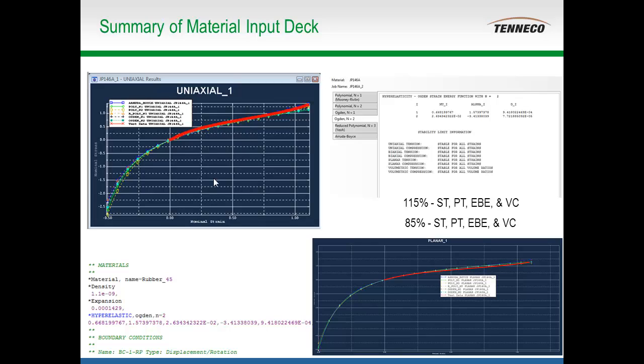So on to the Abaqus analysis. So we take that material data and we will fit, in this case we used an Ogden N=2 fit. This is just showing our fit to our material data. Our hyperelastic test procedures, we have found the best correlation in the pure strain states testing to 85 or 115% strain seem to give us the most accurate correlation to our actual part measurements. Now that strain state's a little bit higher than the part's actually seeing.